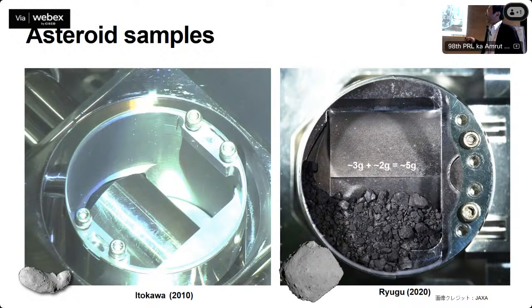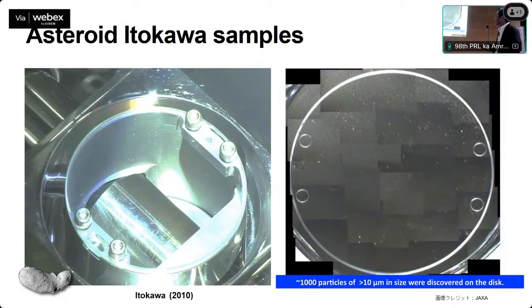Then we covered the sample with silica glass, reversed it and hit it with a hammer. So we found very, very small particles on the glass surface. The average size is about 10 micrometers, very, very tiny. But the number is more than 1,000 particles. So when we analyze the Hayabusa Itokawa samples, we must characterize what these samples are.